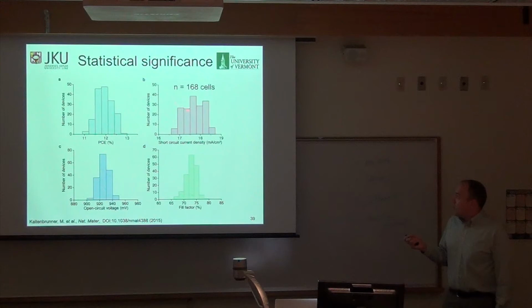So we made roughly 170 solar cells, and we can say that there's a real distribution of efficiencies, of open circuit voltages, fill factors, and short circuit currents that peak around 18 milliamps per centimeter squared, 12% efficiency, fill factor of over 70%, and VOC of around 920.